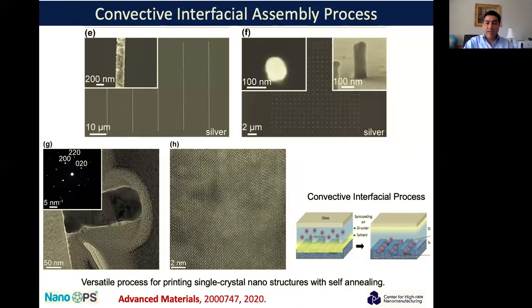And we have done interconnect using the same process, as you can see here. And the surprising thing here is that this is silver, and we got single crystal. So the whole interconnect was single crystal. And this has no annealing required. This was just published early this year. And so we're still trying to understand the process, but certainly we have single crystal, no grain boundary, and no annealing required.